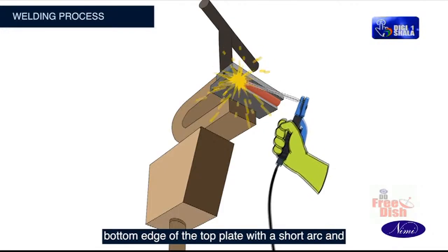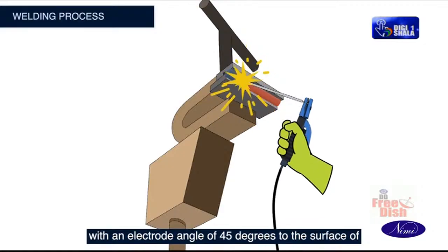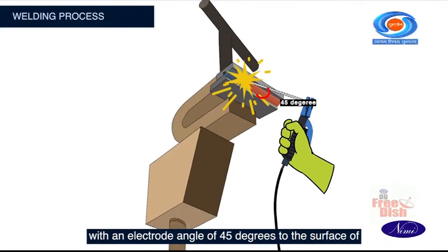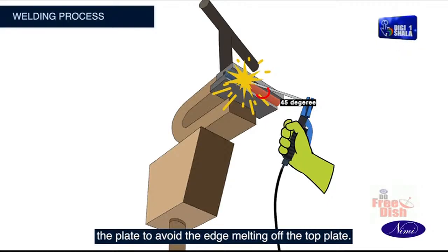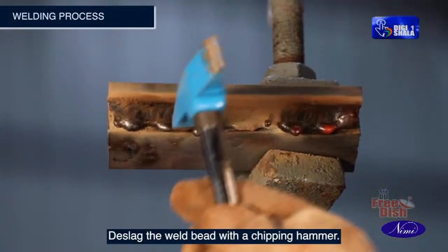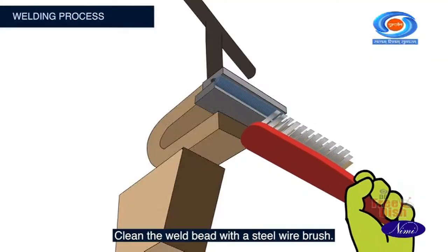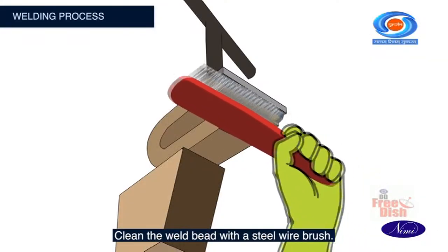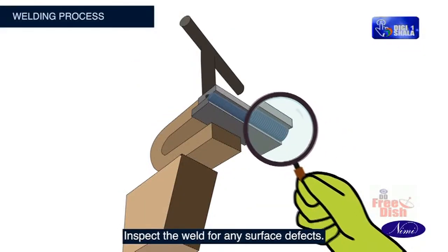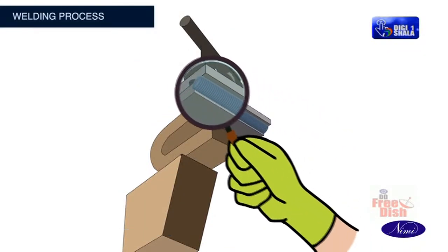With a short arc and with an electrode angle of 45 degrees to the surface of the plate to avoid the edge melting off the top plate. Deslag the weld bead with a chipping hammer. Clean the weld bead with a steel wire brush. Inspect the weld for any surface defects.